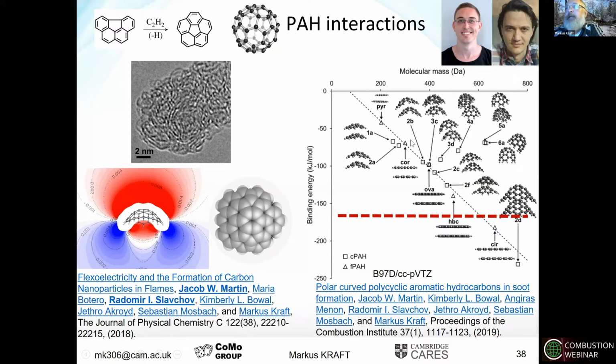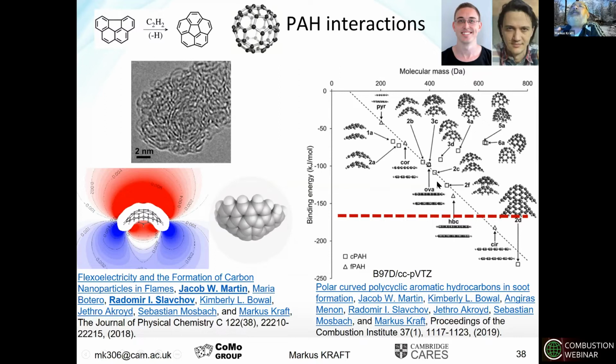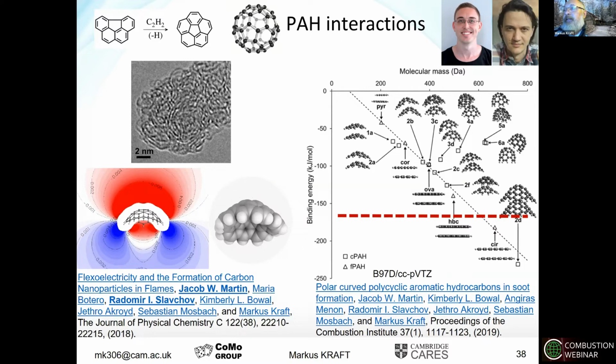Jake worked very hard to produce this figure and calculated, with the dispersion-corrected DFT method, the force between different curved clusters. If you look at this, you see that yes, the curvature enhances the binding force compared to flat PAHs, but it isn't quite strong enough to fully explain particle inception just because of this flexoelectric effect.